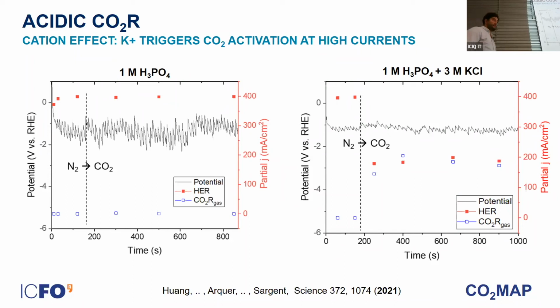So at low current densities, all the cyclic voltammetry with nitrogen or CO2 overlaps. We didn't necessarily see a lot of CO2 reduced products at the low current density. So it's really the case that only when you change your proton source from hydronium to water is this effect more prominent. But I think this still deserves more study, because it's surprising, and more things might be going on in this regime that were not considered here. But for this case, yes.